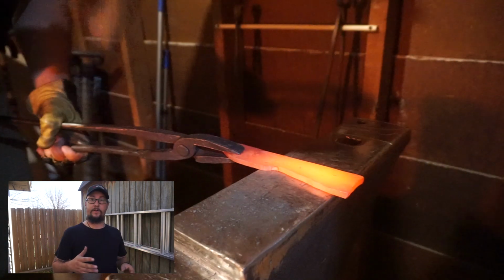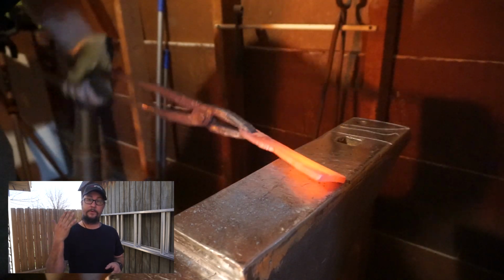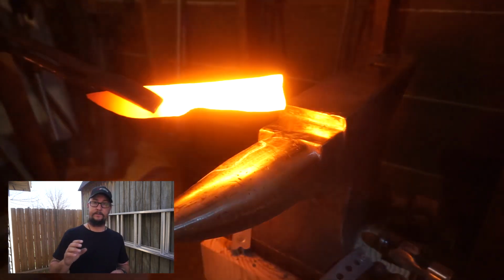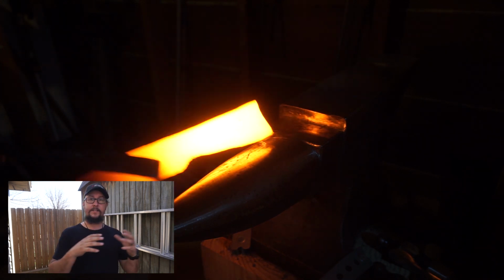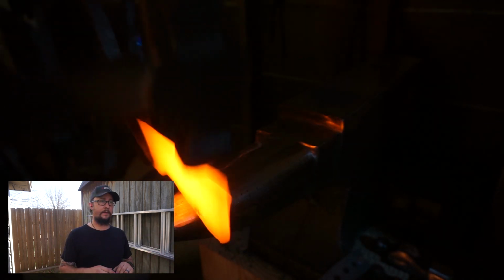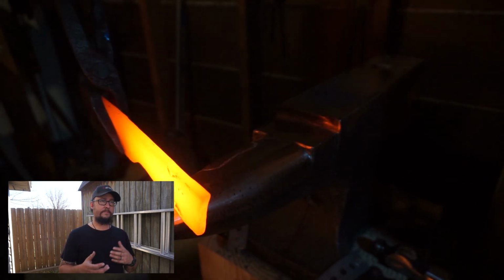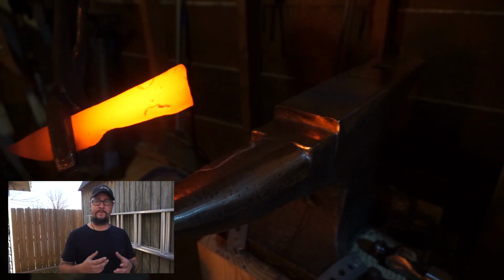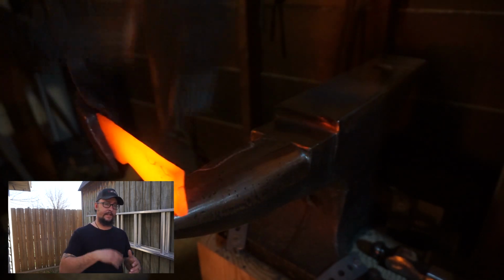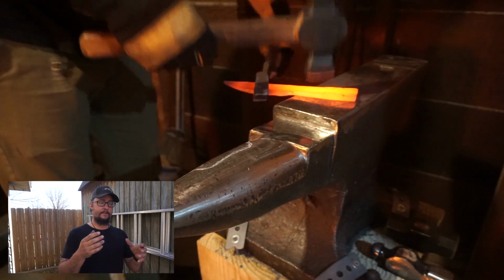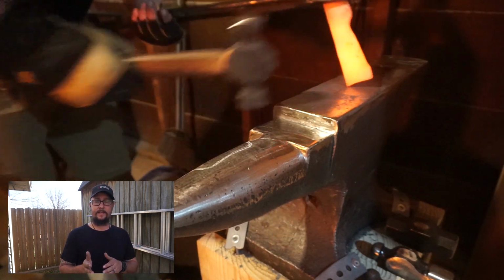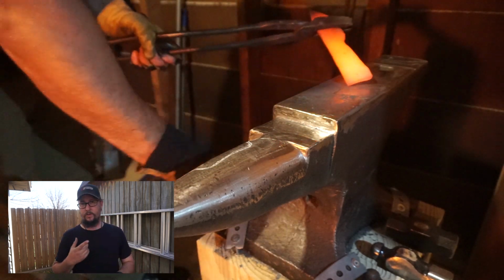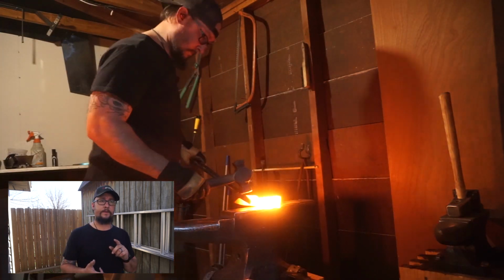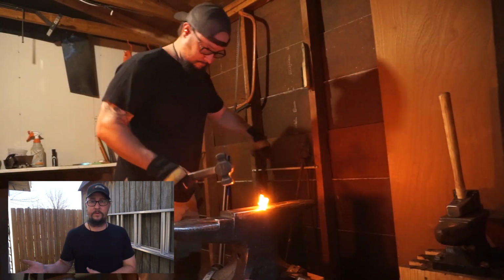And after that, I'm going to go ahead and bring it up to the proper temperature. A bunch of knives have different heat treating temperatures. So for something like 1080, I would bring it up to the proper temp, which is going to be right at about 1520 to maybe 1550 degrees. I'm going to take it up to that, and then I'm going to quench it in something like a canola oil, a peanut oil. I prefer peanut oil. I like that.